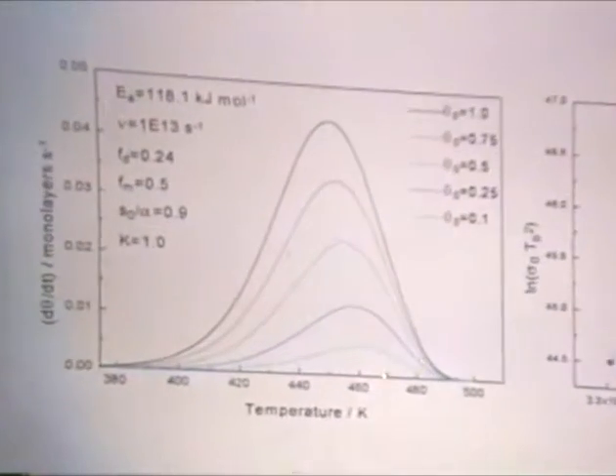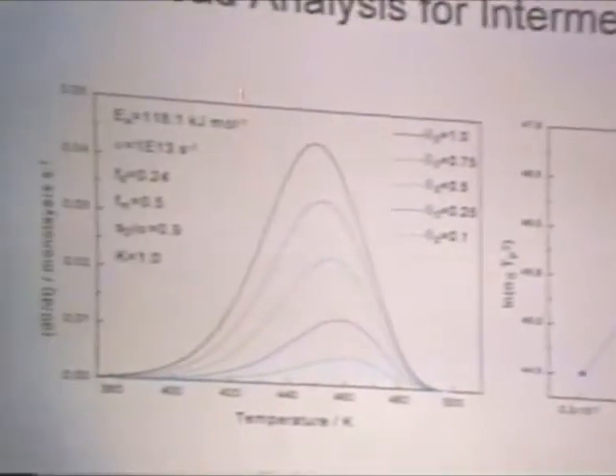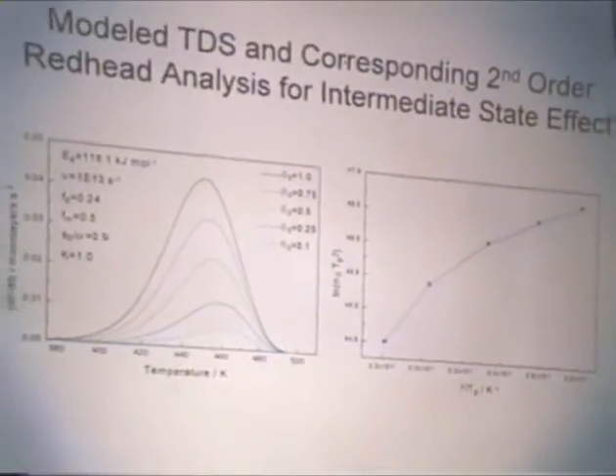So the modeled results, unfortunately, I was not able to come up with a model that predicted a temperature shift large enough to match the experimental results. The temperature shift that I did model was 15 Kelvin. The experimental shift that I observed was 65 Kelvin, so not very close. The data reported by King et al. on platinum 111, they were able to model a large temperature shift, much larger than what we were able to get. And we are currently in the process of contacting them and trying to reformulate our model so that we can predict a large temperature shift.